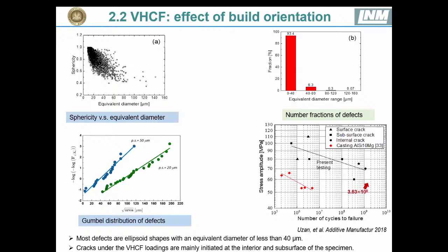And we can see that the defects of them in this material are also analyzed with the Gumbel distributions. And we show that these two distributions here in these figures. And crack and the fatigue property for the additive manufacturing materials is also compared with those of castings. And the specimen is shown here also in this analysis here.